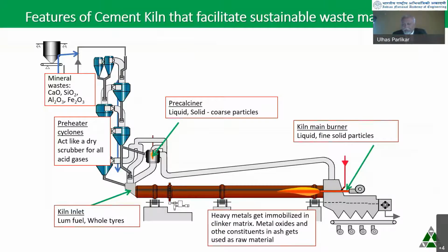The clinker is an intermediate product. That clinker you actually then grind with gypsum, and depending on what cement you want to make, PPC or PSC or a composite cement, you may add fly ash, slag, limestone, etc. So that's the cement kiln part of it.